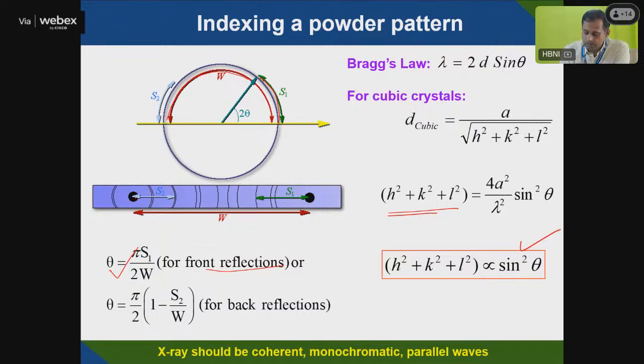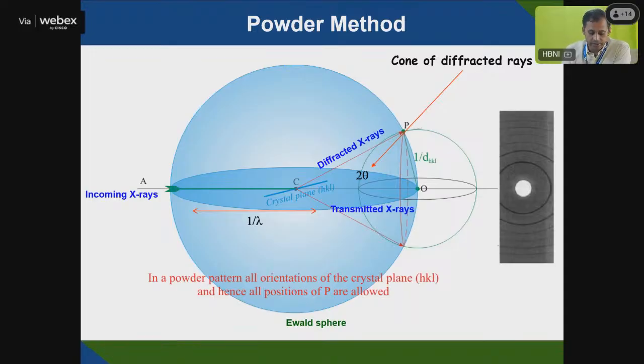So depending on theta, h square plus k square plus l square is proportional to sin square theta. That equation you can find out; we'll discuss how to identify. This I have already discussed: the incoming X-ray is coming here, this is your sample surface, and the diffraction ring is forming a sphere here. Whatever the beam is, you are getting point P, so you'll be able to see that HKL plane.